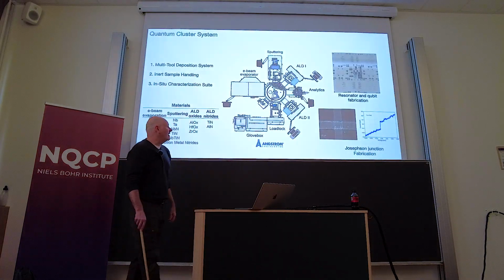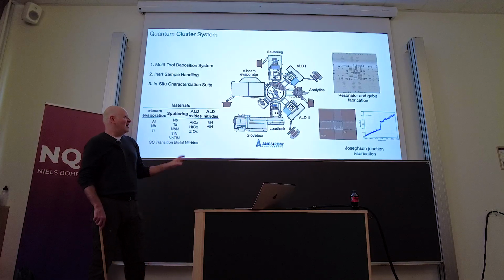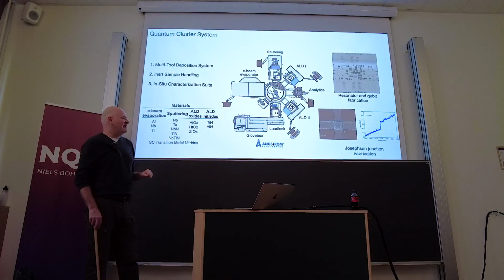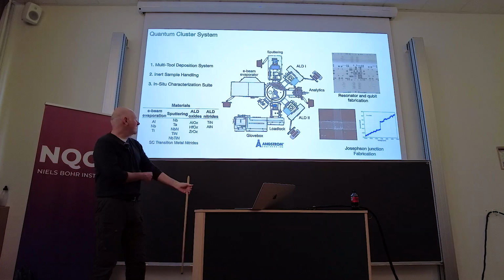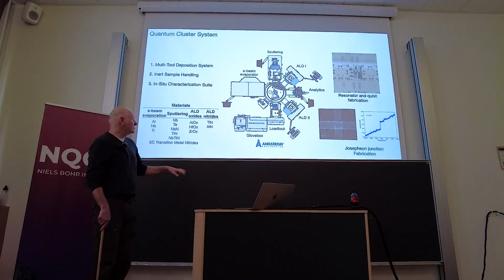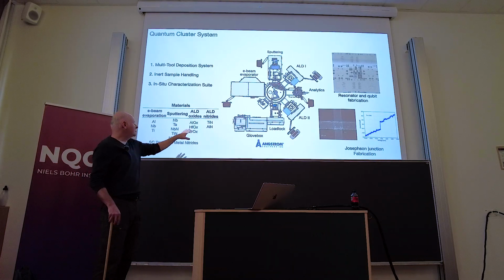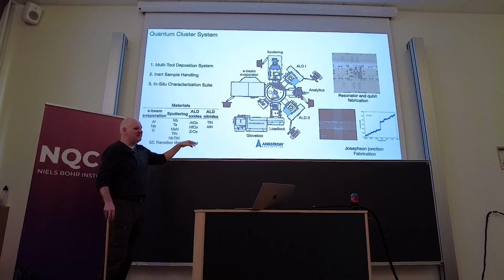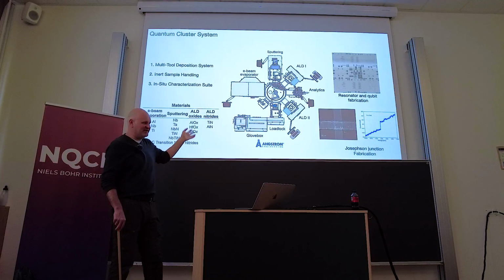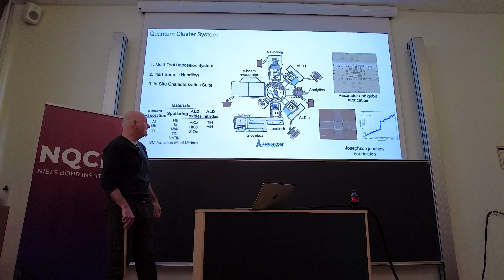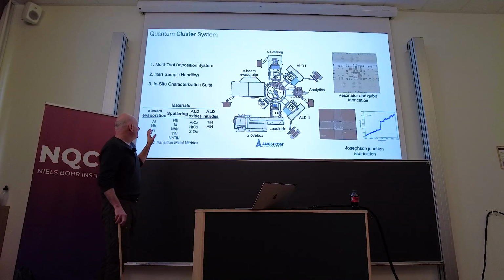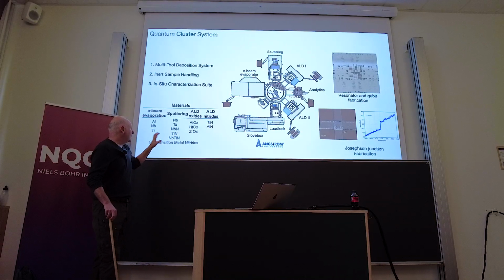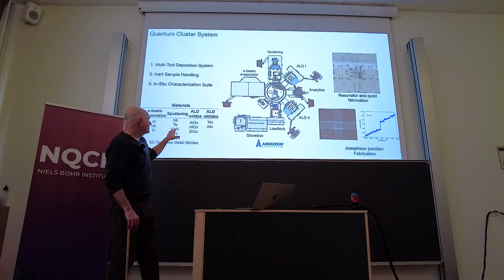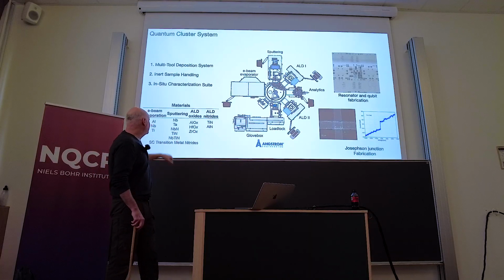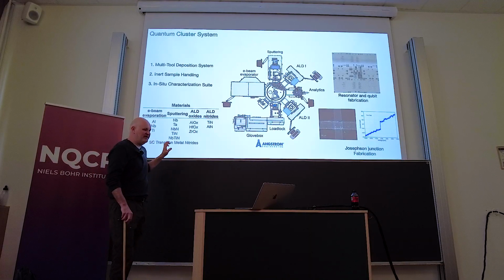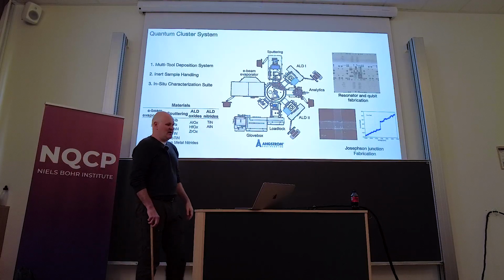Okay, so as I mentioned, this cluster tool allows us to do resonator and qubit fabrication, obviously Josephson junction fabrication. And a few of the materials that we have access to are nitrides: titanium nitride, aluminum nitride, niobium nitride, tantalum nitride, really any of the transition metal nitrides. We can do sputtering, again, of nitrides and metals, oxides by ALD, and then E-beam. Mostly we do aluminum, but we can do niobium and titanium as well.